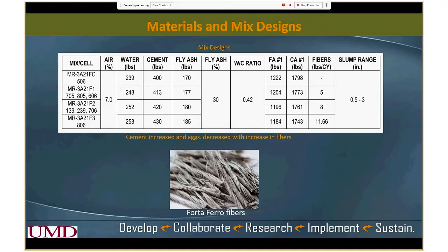All right, so this slide basically provides some information about the mixture. I'll not go into details, but I'll just tell you one thing here: with the increase of the fiber dose, they have increased the cement quantity. You can see for cell number 806, which had 11.7 pounds per cubic yard of fibers, that has 430 pounds of cement.